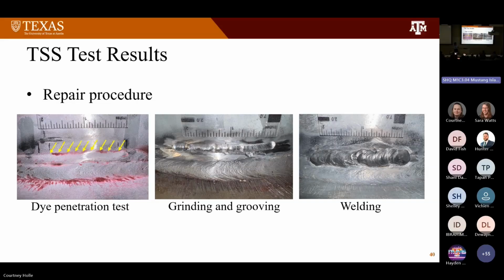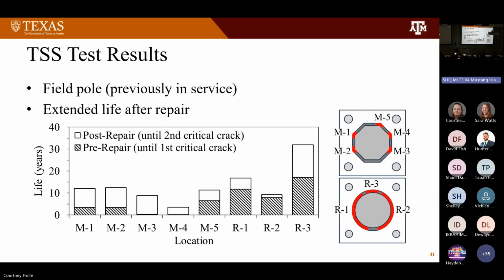The repairing followed this procedure, which has been developed by cooperation of 2 institutions. After some tests, we could get this result. The plot is showing life in terms of years on its y-axis. It was converted by the life conversion using the same methods that Xiu-Chan has explained in the previous slide. In the x-axis, these are presenting the crack locations as explained on the right side. From M1 to M5 are the crack locations on the multi-sided pole. From R1 to R3 are for the round pole.